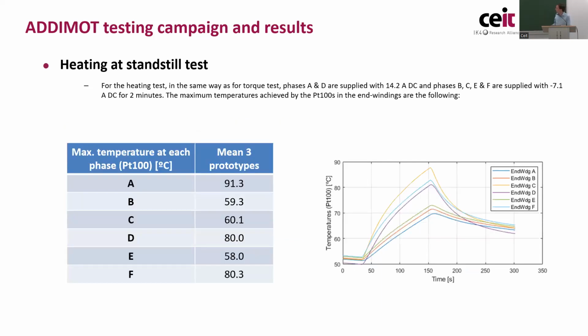Then we proceed to the heating test, also at standstill, providing maximum current for the 8 Newton meter during 2 minutes, which was the requirement from the topic manager. And we verified that the temperatures were under the limits of the insulation system. In fact, it's quite a cold motor, which is very good for the application.